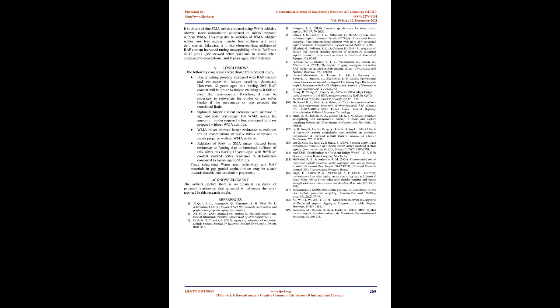V. Conclusions. The following conclusions were drawn from the present study. Binder rutting property increased with RAP content and resistance to fatigue cracking decreased. However, the 12 years aged mix having 30% RAP content will be prone to fatigue cracking as it fails to meet the requirements. Therefore, it may be necessary to rejuvenate the binder or use a softer binder if the percentage or age exceeds the mentioned limits.